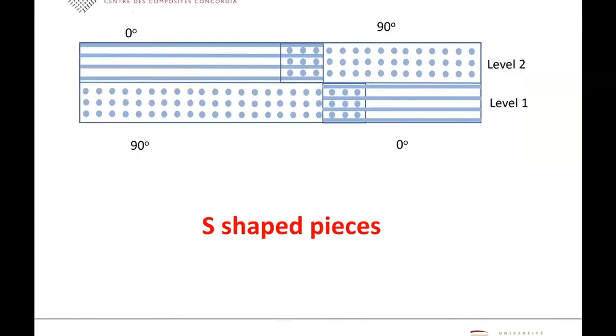So the case of the S-shaped piece, what we do in this case is that we have two levels, level 1 and level 2. At level 1, on the right-hand side, we lay down one layer at 0 degree orientation. And on the left-hand side, we lay down a layer at 90 degree orientation. At level number 2, on the right-hand side, we have a layer at 90 degree orientation. And on the left-hand side, we have a layer at 0 degree orientation. So basically by doing it like this, on the left-hand side you have a laminate that has the 0 degree on the top and 90 degree on the bottom. On the right-hand side, you have the layer 0 degree on the bottom and 90 degree at the top. So these are opposite to each other. By the time you cool it down, again, due to the fact that these different layers have different shrinkage, this piece will curve like this.